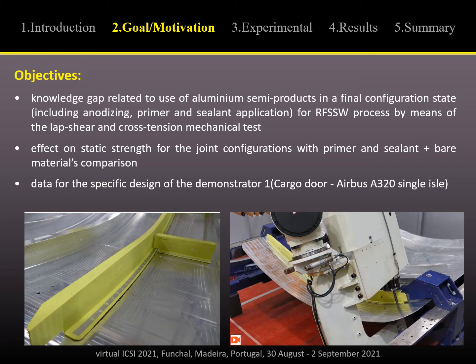Regarding the objectives of this work, it was to fill a knowledge gap related to the use of aluminum semi-products in the final configuration state for the refill friction stir spot welding process by means of lap shear and cross tension mechanical tests, and these states mean including anodizing, primer and sealant application. Then the effect on static strength for joint configurations with primer and sealant was studied and compared with the bare material refill friction spot weld joints.